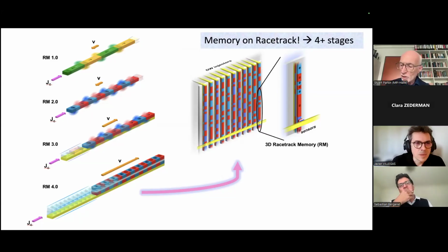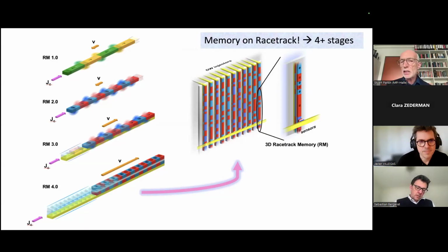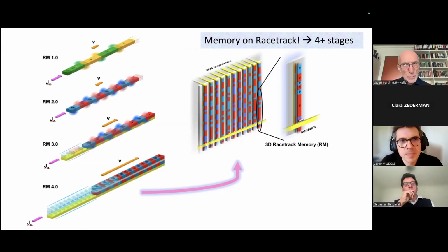In racetrack 2.0, we switched to a multilayer, typically of cobalt and nickel. These layers are very, very thin, so that the interfaces give rise to a perpendicular magnetic anisotropy, and these shrink the size of the domains from hundreds of nanometers in racetrack 1.0 to just a few nanometers in racetrack 2.0. And it turns out the domain walls would move at roughly the same speed, 100 meters per second. So it's independent of the size of the domain walls.